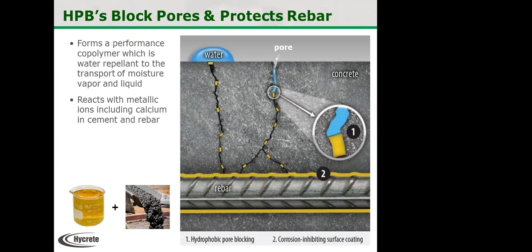They're at the highest level of performance, like Andrew just said. And so the admixture molecule chemically transforms the concrete, becoming a water insoluble polymer. This transformation takes place immediately after it is dosed to the concrete. It reacts with the metallic ions in the cement and the rebar to form a protective layer over the rebar. This is the second method of protection. So we've got our waterproofing protection, then we also have our corrosion protection.